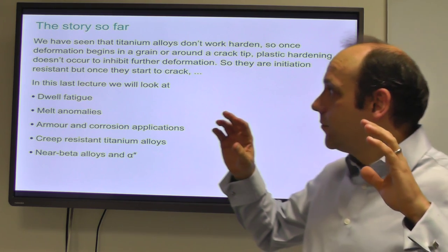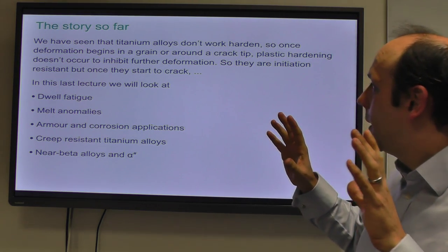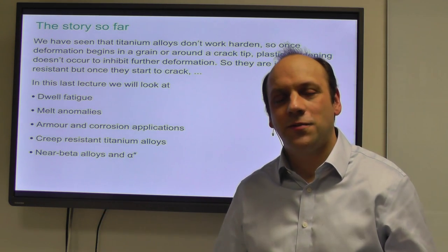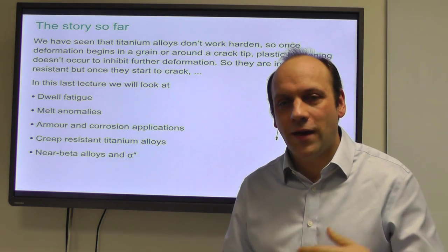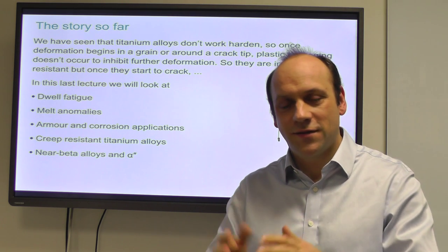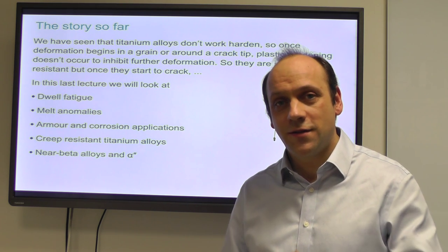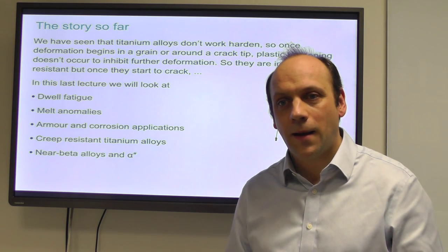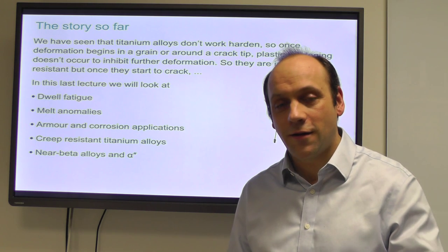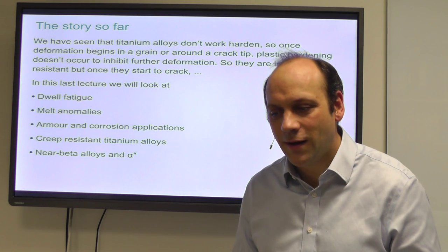But what we've done really so far is we've seen that titanium alloys don't work harden. So once deformation begins, then they tend to suffer from localization. They don't have a lot of cross slip of C plus A slip. So once you start to get prism slip going, then that tends to keep going. They localize. You don't get a lot of plastic hardening around the crack tip.